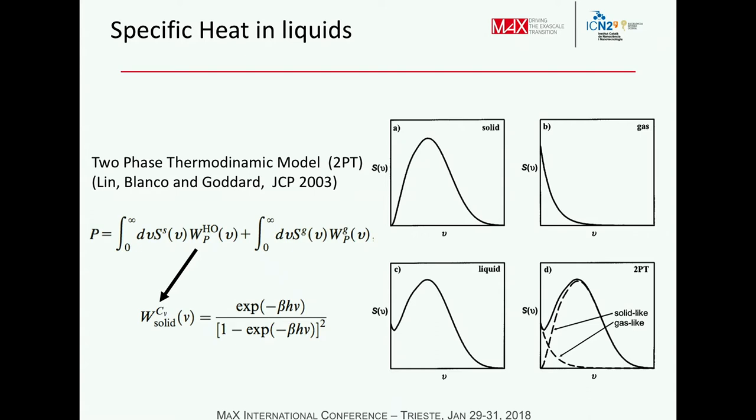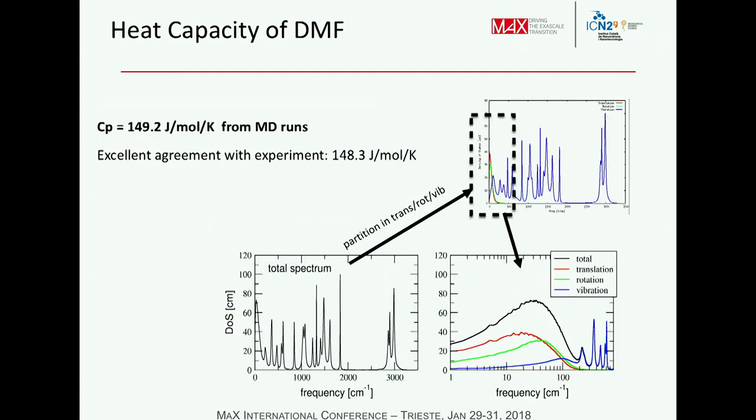And for instance, for the solid, you can use the harmonic approximation using just the statistical quantum weights, and you can get the values for the thermodynamic properties. So, for instance, for the specific heat, you would use this weighting function multiplied by this density of states that come from a solid, which is this one. So we apply this to this liquid, to DMF, and this is the density of states that you get from